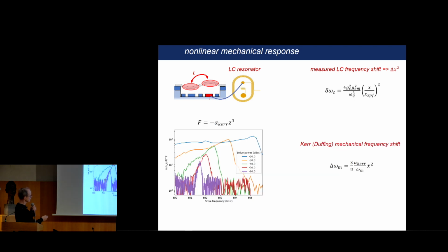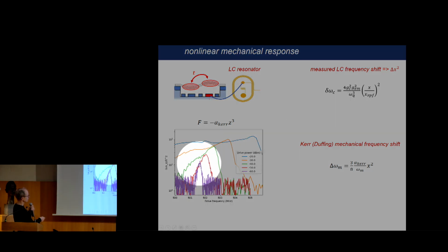So these are the measurements. These are the last measurements that I will show. So here is the response of the oscillator to an oscillating force. So we drive here, we sweep, sorry, the frequency of the oscillating force. And you see that the peaks here are asymmetric. So these are peaks measured with different forces and for different colors. And you see that they are asymmetric, so these are nonlinear vibrations. What you can see also is that the mechanical frequency goes up, and this is exactly what you expect from a Kerr or a Duffing oscillator, so a nonlinear oscillator.